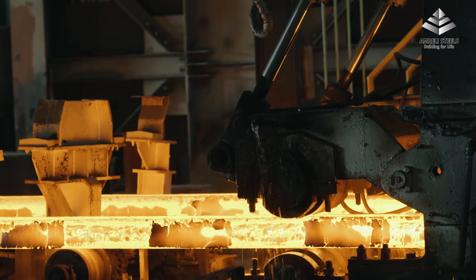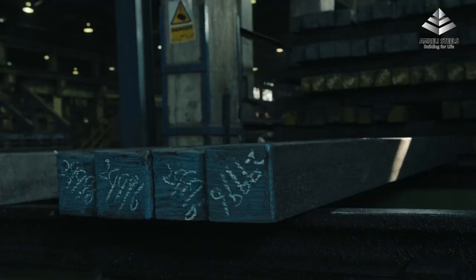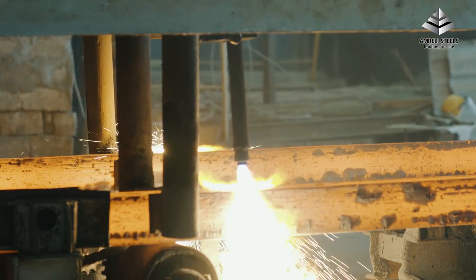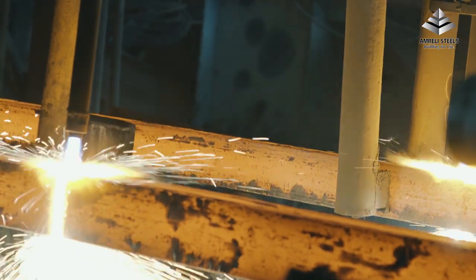The ladle containing the molten steel is positioned at a PLC-based continuous casting machine above the tundish, which feeds the molten metal into molds to cast the billets. The casters have the capability to cast billets of cross-sections typically ranging between 100 and 150 millimeters square. As the billets exit the caster, they are cut to different lengths as required and stacked for cooling.